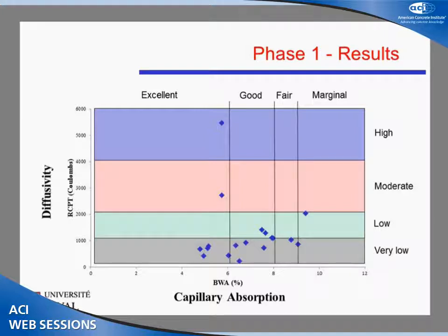The first one, if you look at the little point at the bottom right, this is a mixture that is qualified as very low penetrability, but the mixture would have been rejected because it's marginal, based on boiled water absorption. If you look at the results up there on the top, the mixture would have been classified as excellent based on its boiled water absorption, but the RCPT tells us that it has a high chloride ion penetrability. So this graph points out that the absorption test can lead to misleading information. We wanted to understand why these data were so scattered, and we realized that all the mixtures in the cloud down there contain silica fume. The mixture here contains fly ash, and the one up there contains only ordinary Portland cement. So we see the influence of supplementary cementitious materials.